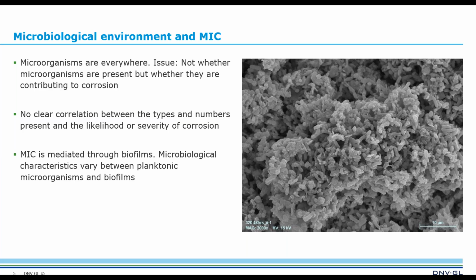We have these microbiological methods that help us determine what's present, if they're active, and different types of species that are present. We have more traditional methods like culture testing that can tell you how many of a certain type of microorganism are present. But those tests aren't able to show a clear correlation between numbers or types of microorganisms and whether you have corrosion and what the severity might be. So say you find 10 to the 6 bacteria present on your pipeline, that doesn't readily correspond to a corrosion rate. That's one of the more difficult challenges with MIC, that it requires a lot of evidence and testing to determine if your microorganism population is contributing to corrosion. We'll talk about that a little bit in the next few slides.